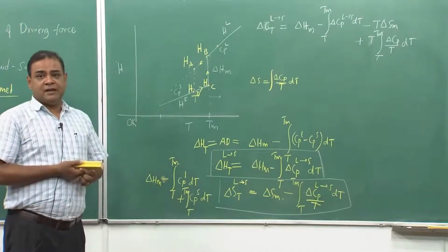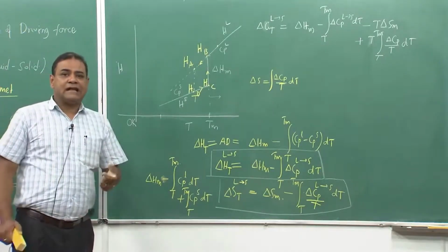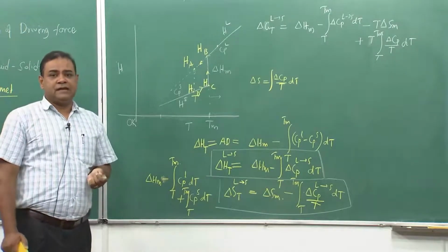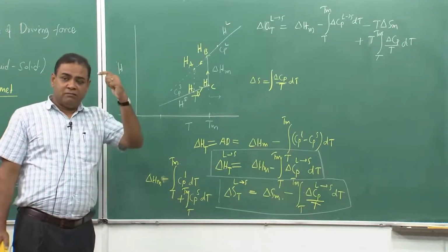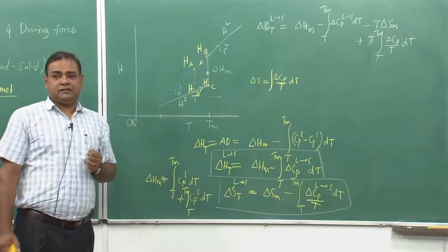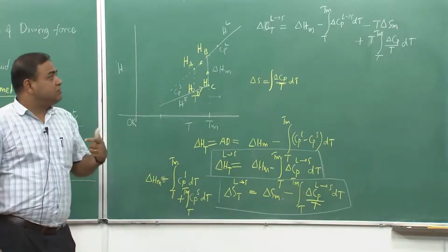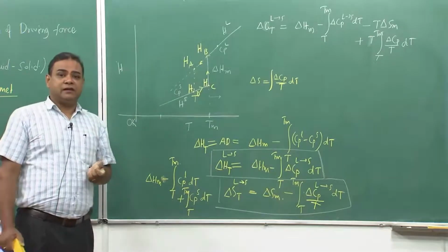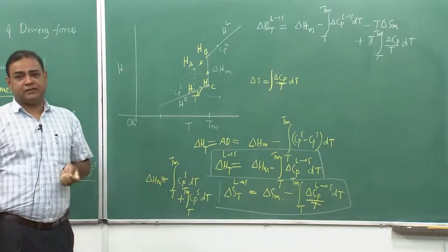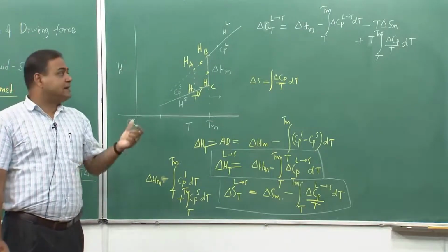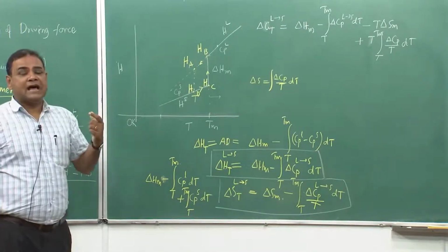We will talk about the nucleation term later, but for your information, let me tell you about liquid water. We have seen that once we take it to 0 degree Celsius, it solidifies. But actually the liquid water can be maintained liquid even below minus 40 degree Celsius.